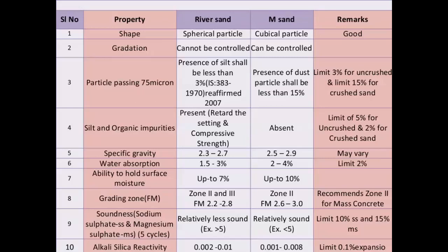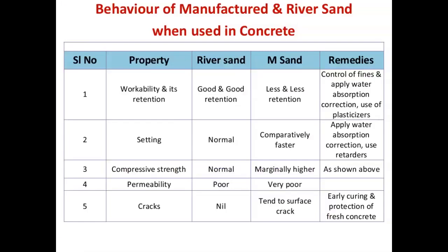For that also, to rectify this problem, we can apply water absorption correction and we can use some retarders. When you see the compressive strength, with river sand it is normal, whereas for M sand, as I said, because of the better particle packing, it has a higher compressive strength. Permeability is poor in the case of river sand. That also we can address through early curing, and when we do early curing, that can also be minimized.